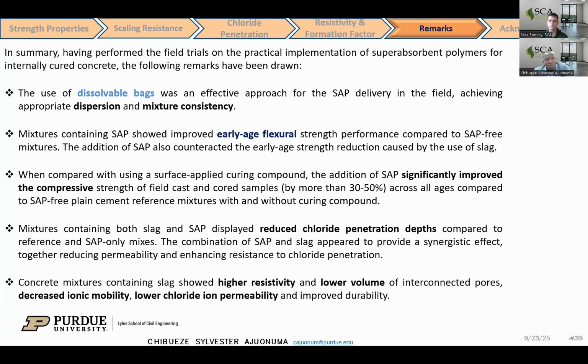And then also, most especially, we saw that mixtures containing slag and SAP displayed reduced chloride penetration depth when we compare with the reference mixture and the SAP-only mixtures. So we find out that the combination of SAP and slag appears to provide a synergistic effect, together reducing the permeability and enhancing the resistance to chloride ion penetration. Most especially, there was also higher resistivity in mixes containing slag. This shows an improved durability.